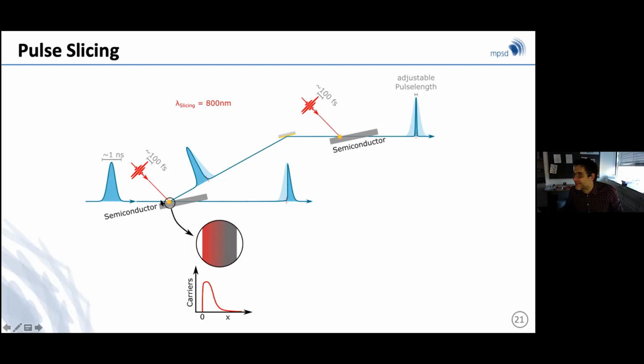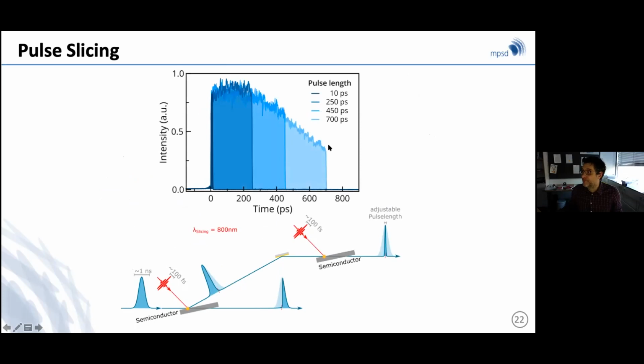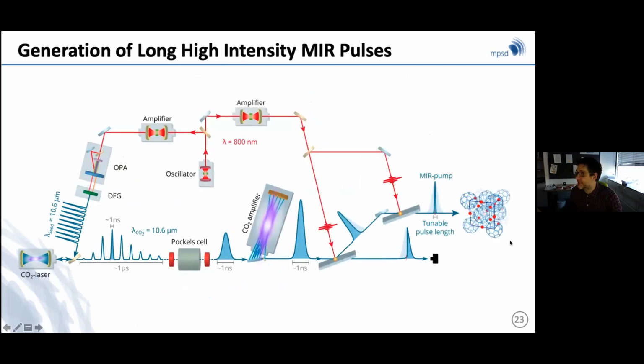So the excitation of the semiconductor makes a semiconductor, which is usually transparent, opaque. And so what I can do is slice the front and the back of this pulse, again, in a way that is absolutely synchronized to an external femtosecond laser, with very nice, controllable, sharp edges. This is a little harder than what it looks like, but conceptually it's straightforward.